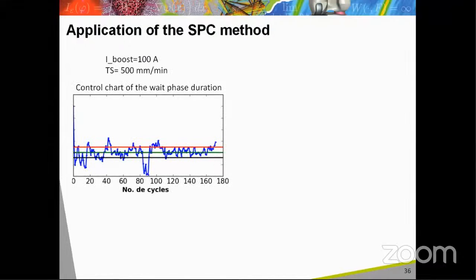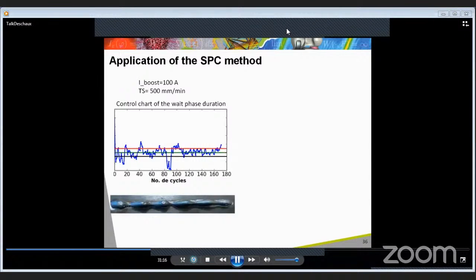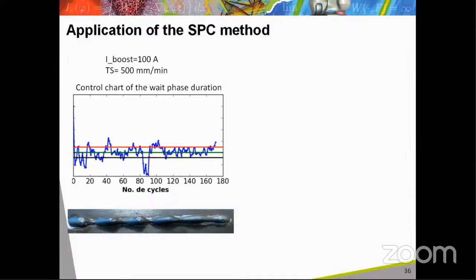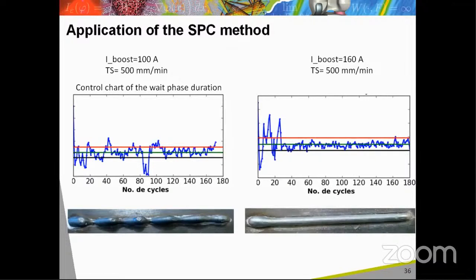Here is a control chart computed for the duration of the wait phase. This control chart indicates a process out of control, several points of the control chart being below or above the control limits. This result is confirmed by the observation of the irregular deposit. This kind of height variation of the beads is generally due to a too low arc current. For the next deposited layers, the current of the boost phase has been increased to 160 amperes, allowing to improve the regularity of the bead. The control chart of the wait phase duration indicates a process under control, except at the beginning of the bead, due to an accumulation of metal produced by the initial cycle.